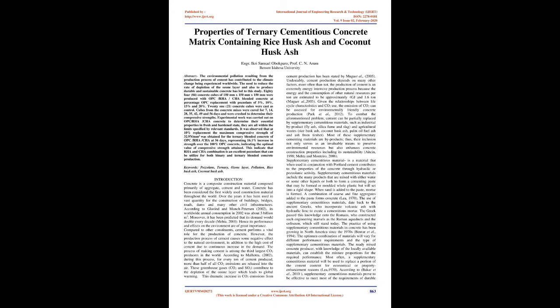Concrete cubes of 150 mm x 150 mm x 150 mm were produced with OPC/RHA/CHA blended concrete at percentage OPC replacement with pozzolans of 5%, 10%, 15%, and 20%. Concrete cubes were cast as control. Cubes from the concrete mixes were cured for 7, 14, 28, 35, 42, 49, and 56 days and were crushed to determine their compressive strengths.